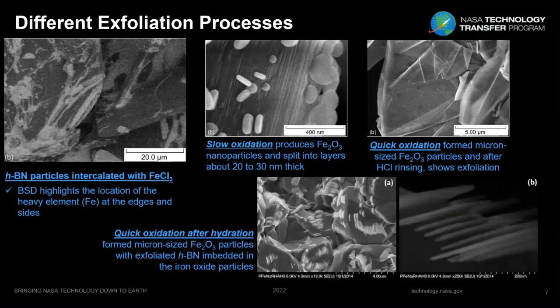with the iron chloride. We have many ways that we can do exfoliation that give different products. If you take the sample and you do a slow oxidation, meaning that the sample was placed in the oven, and then the oven was turned on and the temperature increased slowly until the desired temperature, you create, as the middle picture shows, smaller particles of iron oxide. These are nano-sized particles. And the layers of the boron nitride are starting to get split in the 20 to 30